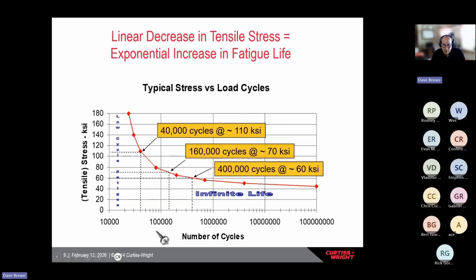I did mention a dual peen, where a secondary shot drives in a little bit more compressive stress. The more compressive stress that goes in, the less net stress experienced by the part. But if it goes from 70 KSI to 60, that's not that big of a decrease.